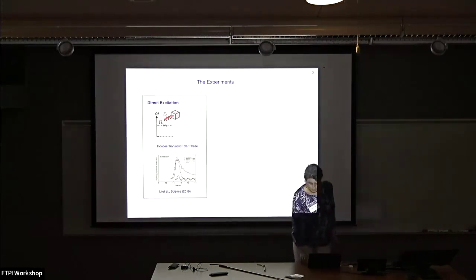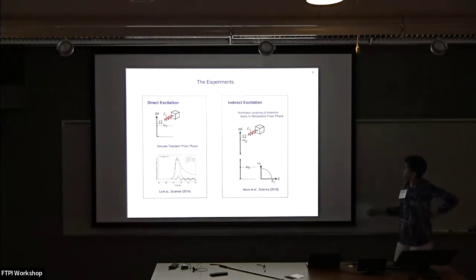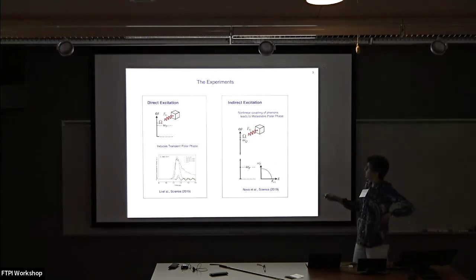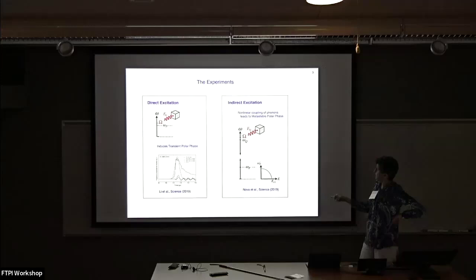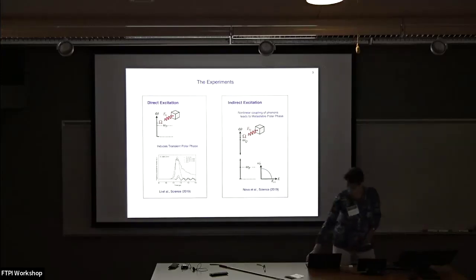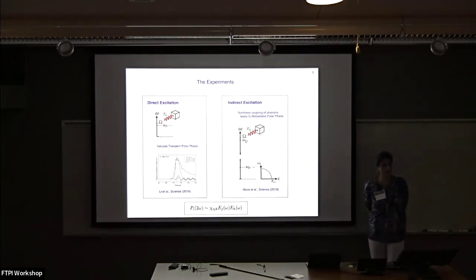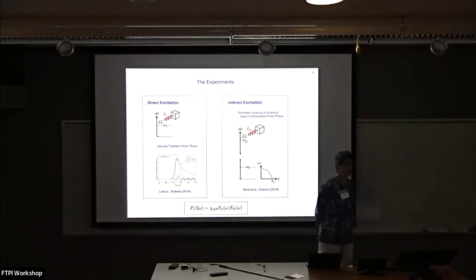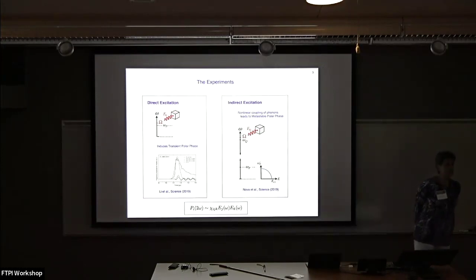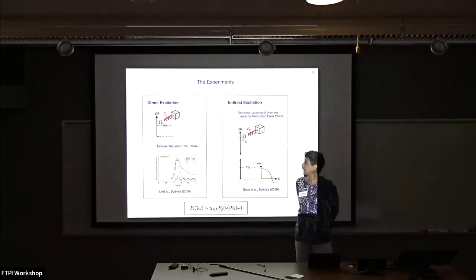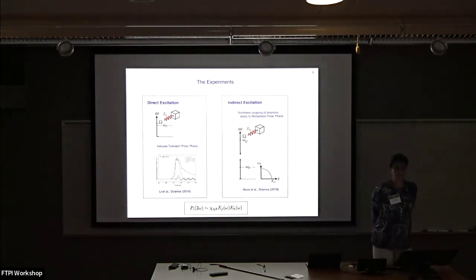And what the MIT group saw was that that induced a transient polar phase. Now, the work that was done in the Hamburg group, Andrea Cavallari and colleagues, is slightly different. What they did was they resonantly pumped a high frequency optical mode that was anharmonically coupled to the polar mode and drove it soft. And how did they know that they got it soft? Well, they looked at second harmonic generation. And that told them that in fact, the system had broken inversion symmetry, and since strontium titanate is really well understood,